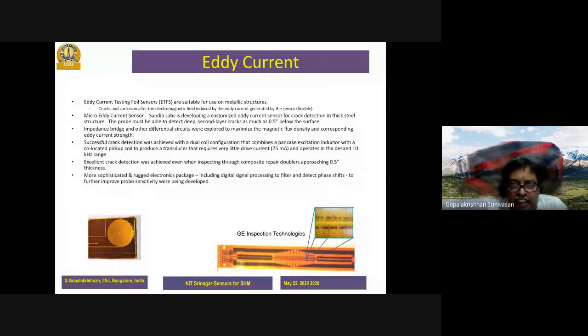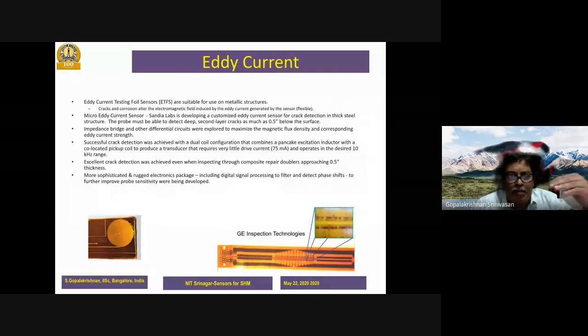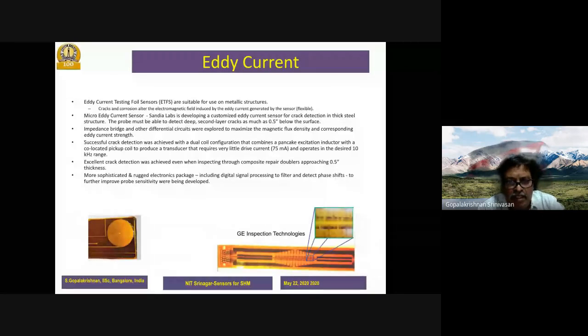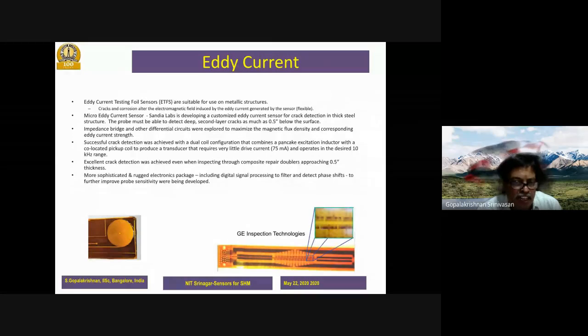structure. For example, in a laminate, you have a number of different lamina stacked together. If there is a delamination at, say, the fifth interface, at the fifth lamina, you cannot monitor it from the surface, mainly because the eddy current will not penetrate that deep. But this was a technique that was used very successfully to monitor surface cracks. GE holds the major patent in this. They are the leaders in this technology. Most of the equipment that has come here is from GE.